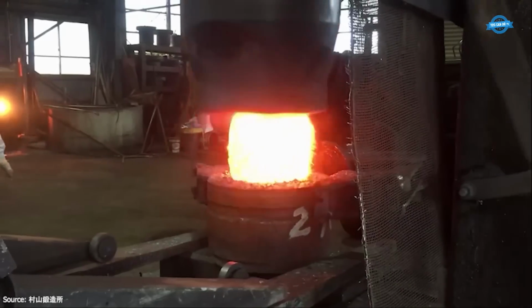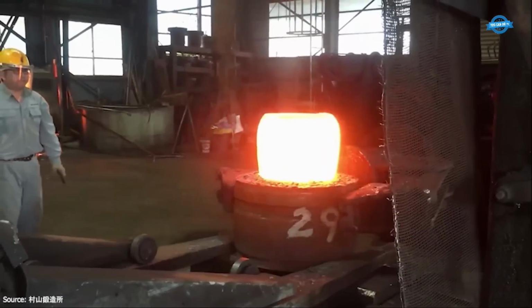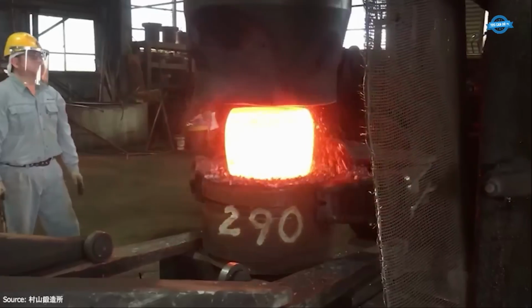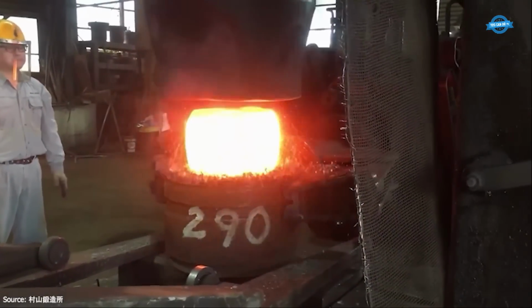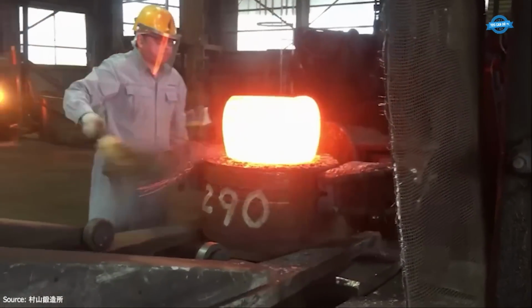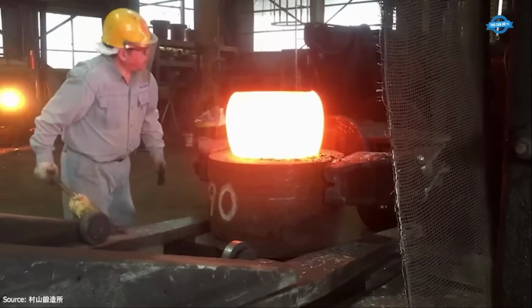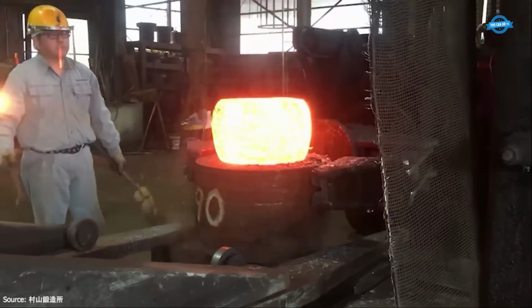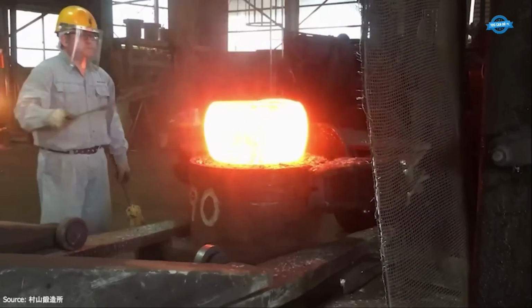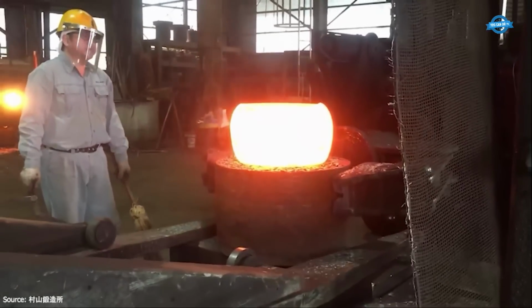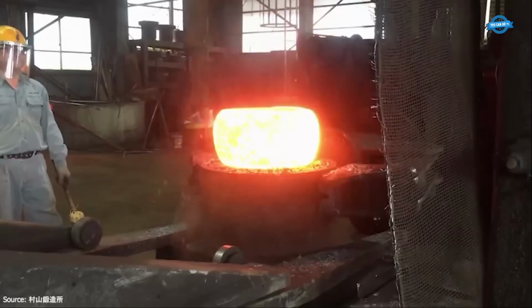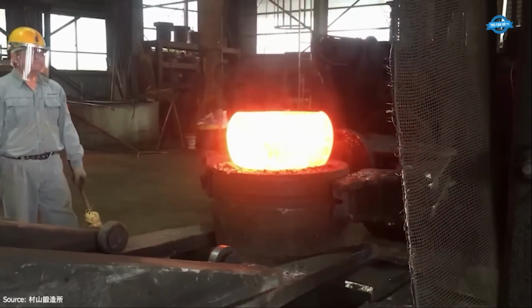Surface scale, which forms as a result of the billet's exposure to oxygen at high temperatures, is removed. This descaling is critical. Leftover scale can cause surface flaws or inclusions during forging. Descaling is performed using a combination of high-pressure air jets and mechanical scale breakers to achieve a clean, defect-free surface. The forming process officially begins.